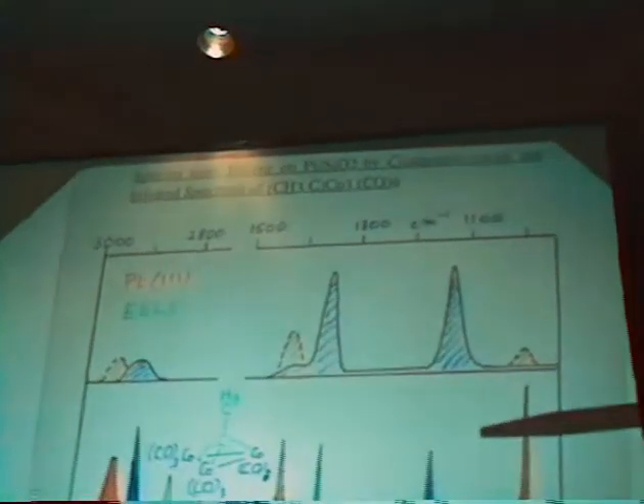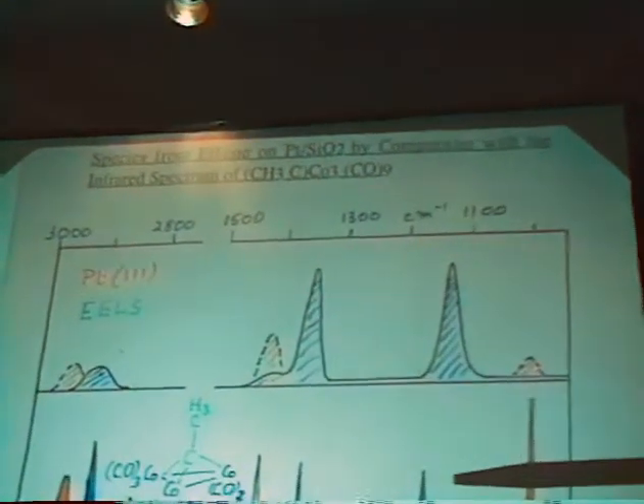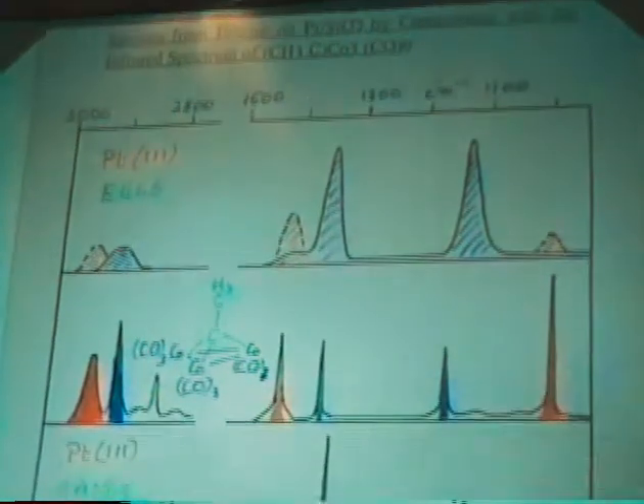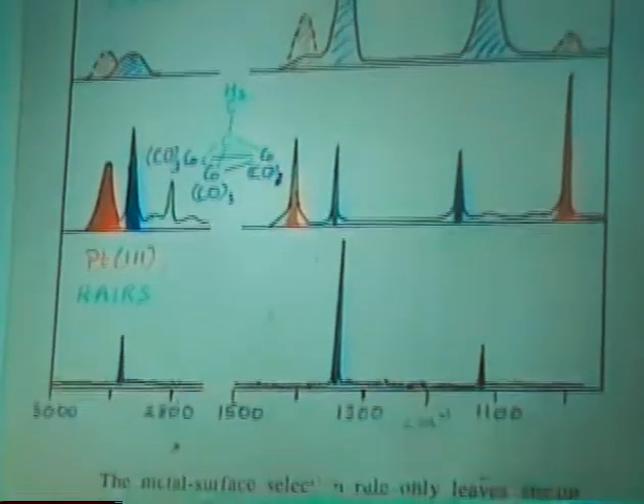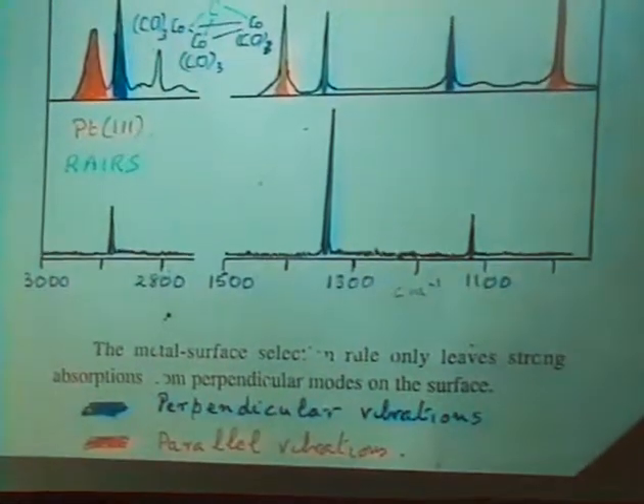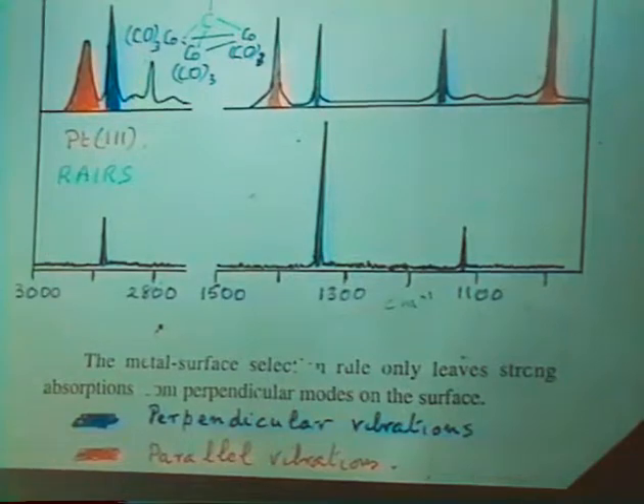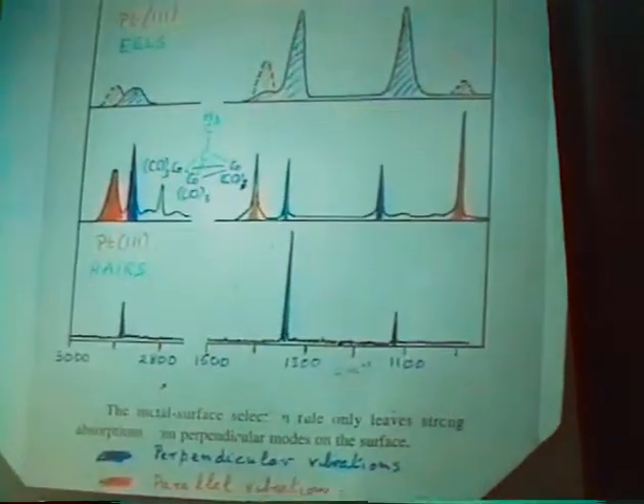Here are the electron energy loss spectra I showed you before, the spectrum of the model compounds with the parallel and perpendicular modes, the parallel ones only showing up off specular in EELS. And then the spectrum here was very poor from EELS. Here it's beautifully sharp. You get magnificent resolution.